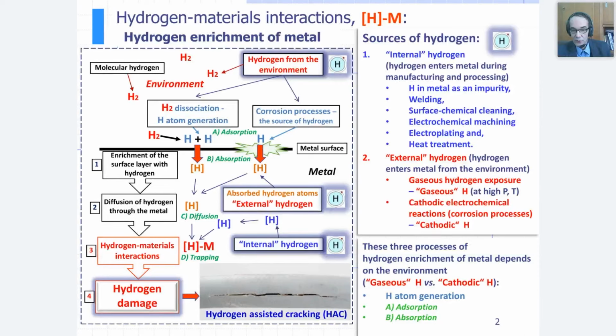It is important to note that these three processes, A, B, and C, marked in green, adsorption and absorption, but also hydrogen atom generation, as you can see in the down right part of the slide, are different in the case of gaseous hydrogenation of material and cathodic hydrogenation of material. So we have a difference if the source of hydrogen is hydrogen gas or a corrosion process.